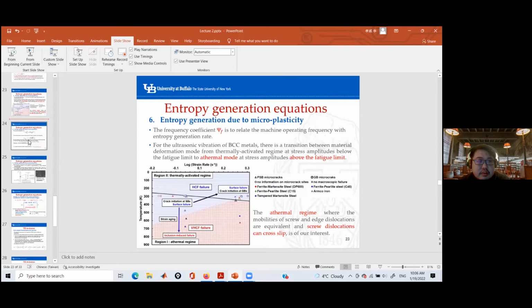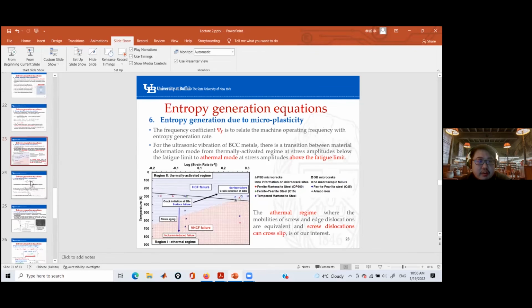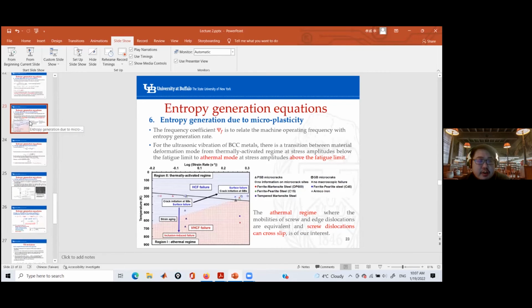We are in the viscous drag region, I feel. Oh, you mean the frequency that will actually activate the frequency? The frequency when there are two dislocations, but they will not see each other because the frequency is very high. But they may see the lattice vibrational drag. So there will be some cutoff frequency between these two. That means below a certain frequency, lattice drag will be there, plus dislocation interaction will be there. But above a certain frequency, only phonon drag will prevail. So that is something there on this. Maybe it may not be there in the frequency we tested. At very high frequency, it may be there. Okay.